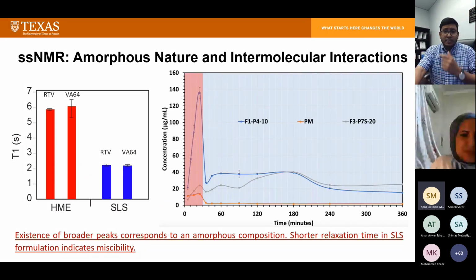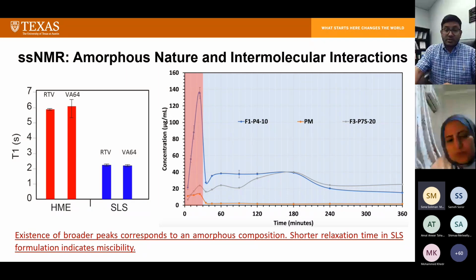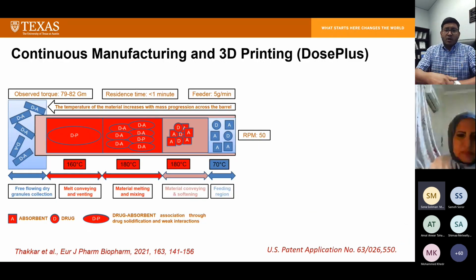And most importantly, we found that our 3D printed tablet showed a 21-fold increase in dissolution of the poorly water soluble drug compared to the physical mixture or the bulk drug. So it was really a good summary of our technology.